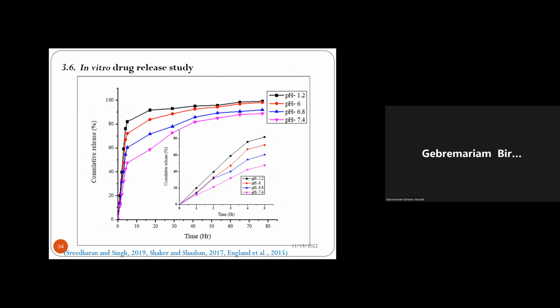And finally, we determined the in vitro drug release profile of the ciprofloxacin from the nanoparticles at various pHs. And as you see, the various pH values give different drug release profiles, and majorly at lower pH, especially at a pH of 1.2, there is a burst release. Almost more than 80% of the drug was released, and then the trend continues like that. But at a higher pH, like 7.4, below 50% of the drug was released before 10 hours, and it increases in a controlled manner. So that one is the best pH for the release of the drug.